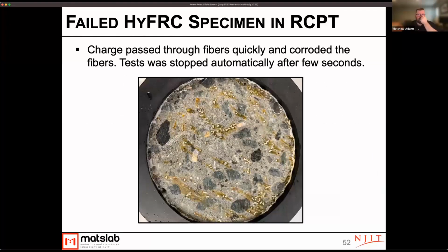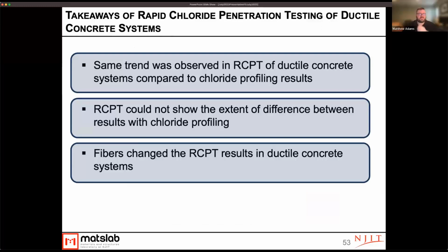And here you can see that HyFRC system that we did with the fibers still installed, and you can see those fibers have basically corroded in that test method, and that test method is only about 6 hours long. It started to corrode them immediately, and we basically had to stop the test after a few seconds because so much charge was being passed in that system. So in general, we did see the same trends, but the fibers can have an impact, and we really need to understand those systems long-term to get more information on how RCPT can be used.